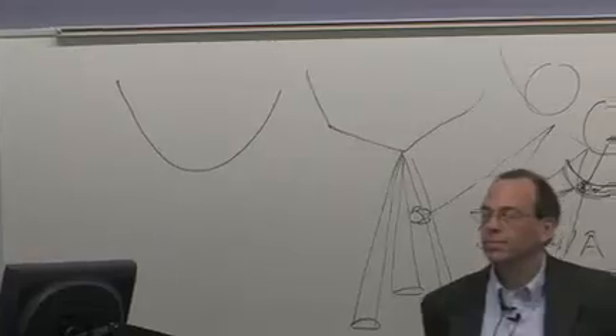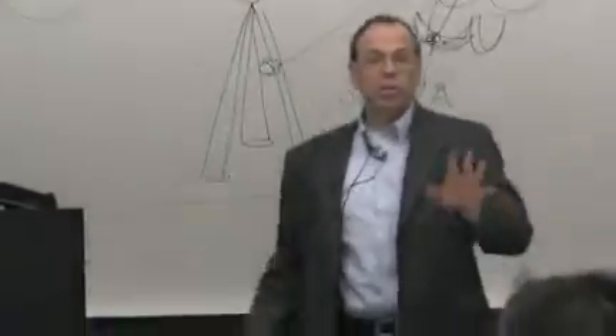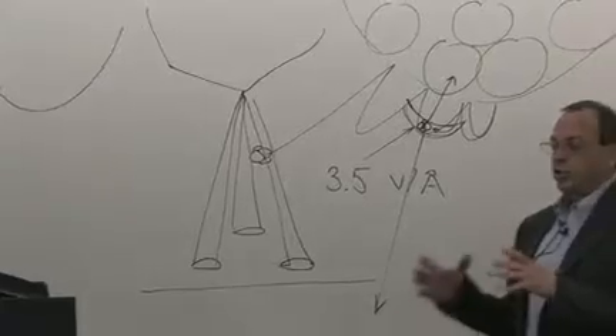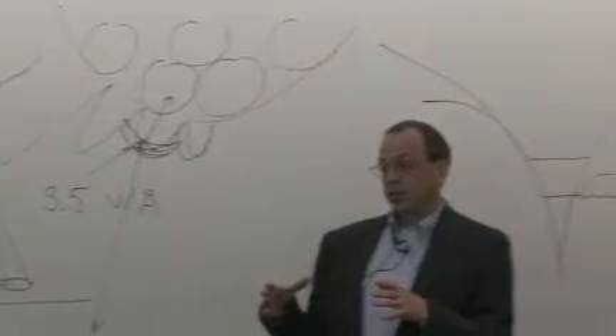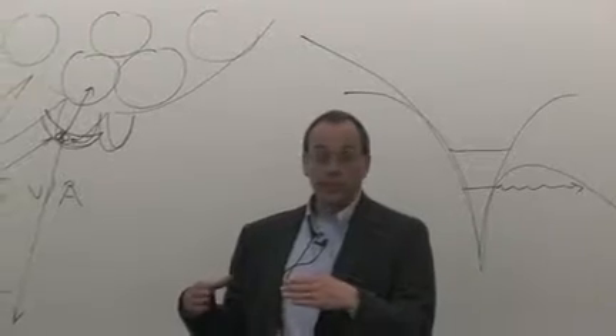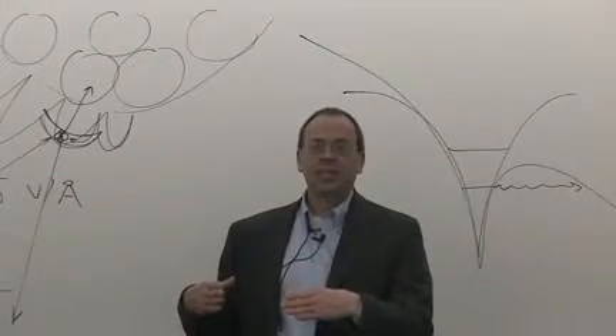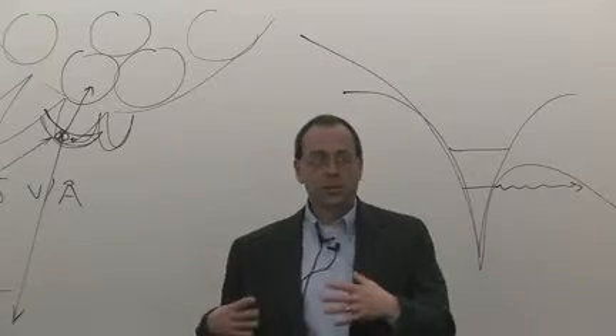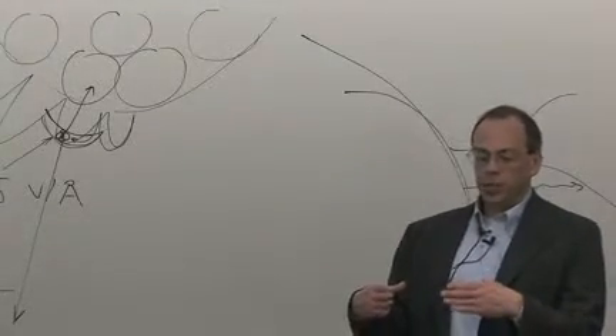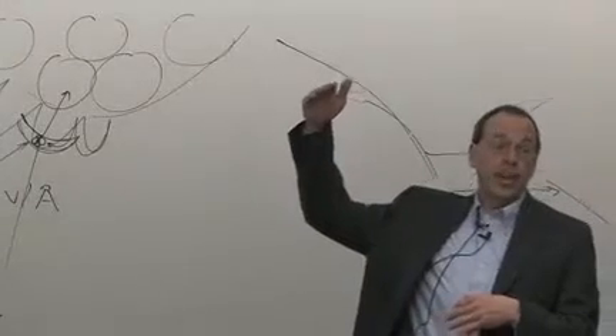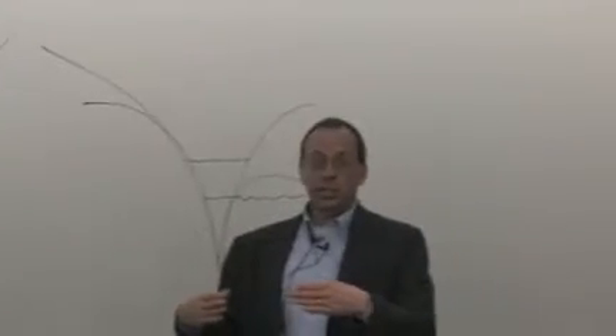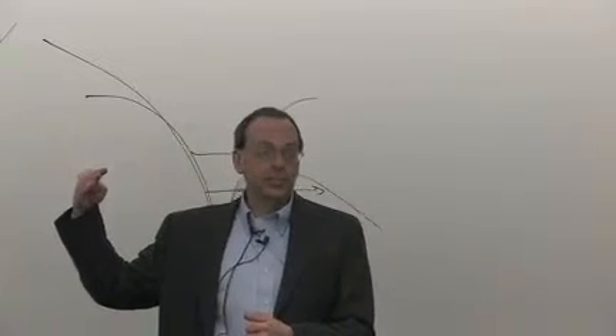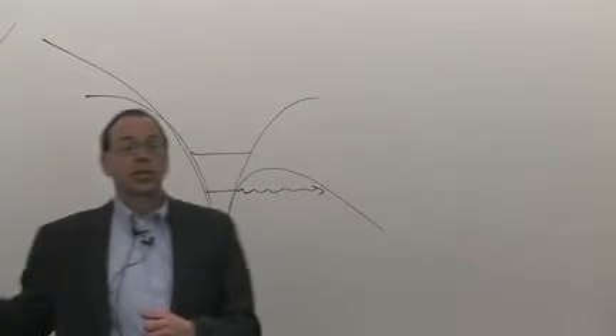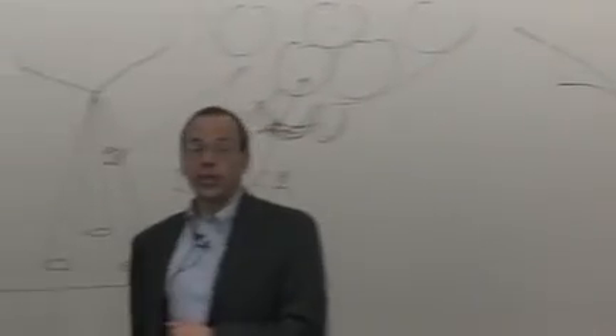We don't have an ultra-high vacuum chamber, though. I should clarify that, we typically get the sample chamber as clean as we can, because contamination is very critical if you've got a real surface imaging instrument, and that's what we've got. So we found out how to clean everything and keep our vacuum cleaner than any SEM has ever been for the sample area. Up in the gun area, it is ultra-high vacuum. In the sample chamber, it's typically in the 10 to the minus 7 range, so pretty good vacuum. Up in the gun area, it's cryogenic. It might well be in the 10 to the minus 10 torr range. We don't have a gauge up there, but certainly when you've got a cryogenic surface, there's terrific pumping speed.